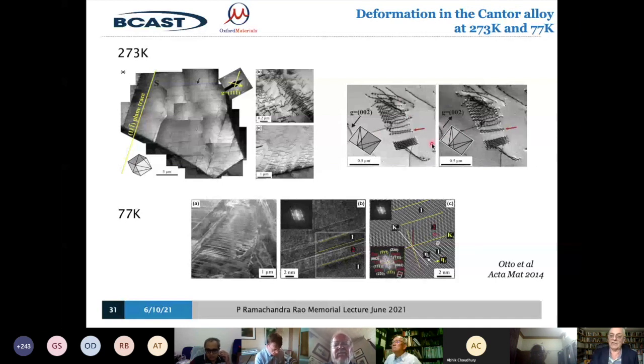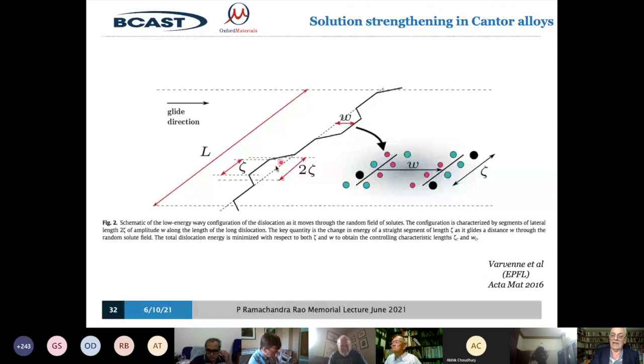Well, of course, I've given the game away because I've been talking about these local environments. If we have a dislocation line here, it gets held up by the locally strained regions. It's got to push its way through these different sized atoms in their local strain fields. And that is quite hard to do. So it still can be stretched and deformed and formed. It's still got that wonderful ductility, that wonderful malleability, that wonderful resistance to fracture, but it does it at a much higher strength level because of the intrinsic difficulty of pushing the dislocations through the structure. Here's a complicated equation. Bill Curtin at EPFL came up with the basic maths to explain this.